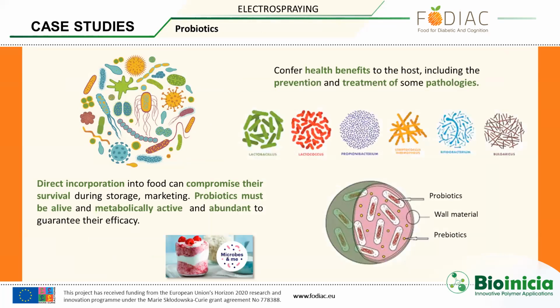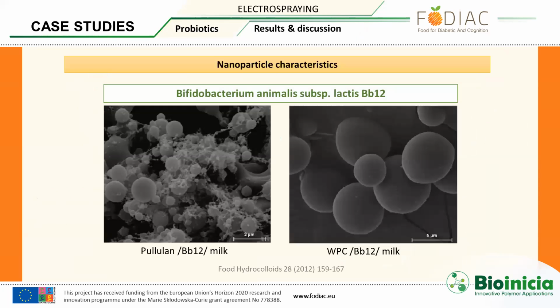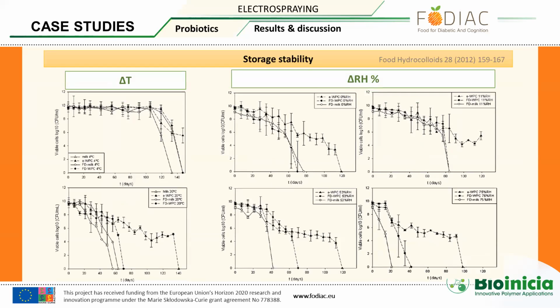We have also encapsulated probiotics, and this poses a challenge because the probiotics need to arrive in the food product alive, metabolically active and abundant to be effective. So we have encapsulated Bifidobacterium animalis in pullulan and whey protein concentrate, obtaining microparticles. Studying the storage stability at different temperatures and humidities, we observed that the capsules always provide a higher stability in comparison with the freeze-dried bacteria.